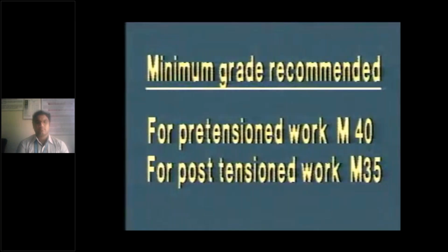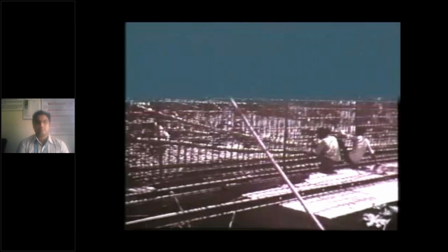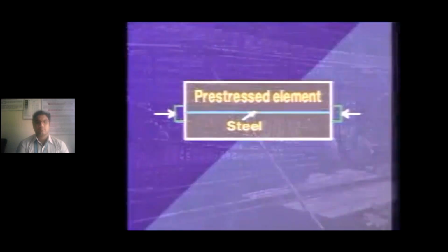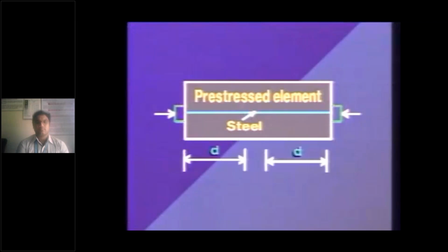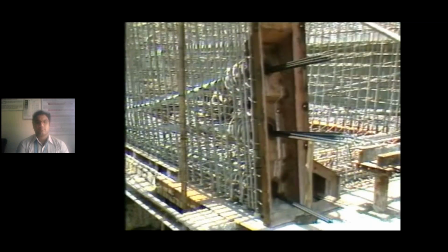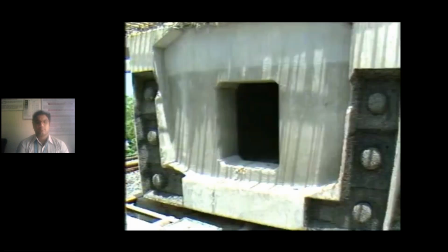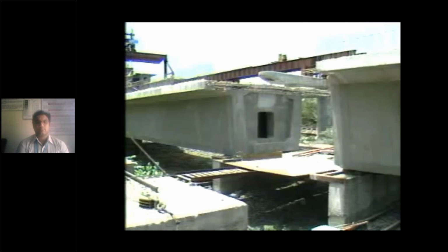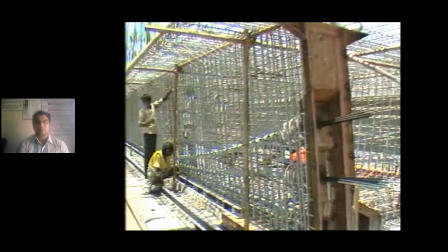In pre-tension construction, the pre-stress is normally transferred to the concrete by a bond over a length, which may be equal to the member depth. No problem arises due to the gradient stress input. On the contrary, for post-tension elements, the pre-stressing force is transferred through the bearing of the end anchorages and applied in full at the extreme end of the element. Hence, the end zone of the elements called end blocks have complex stress concentrations.